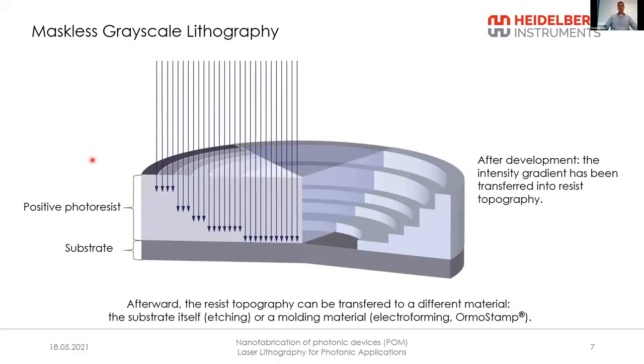The other main application of the DWL systems is the grayscale lithography, as I mentioned. In this mode, we basically modify or modulate the intensity of the pixels while moving across the substrate. So for each pixel, we can control the intensity and define how deep the resist will be exposed. And when you do the development of the resist, the features will appear according to the intensity that you apply to each pixel. This mold in the photoresist can then be transferred into the substrate by etching, or you can use it as a master and do electroforming, or use something like a stamp to create a negative that you can use for further processes.